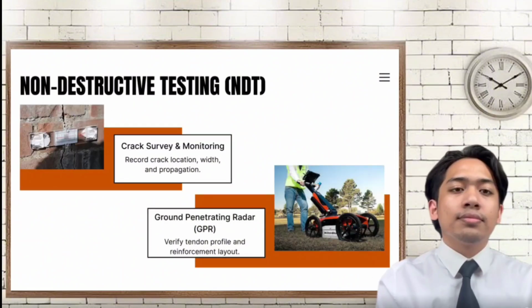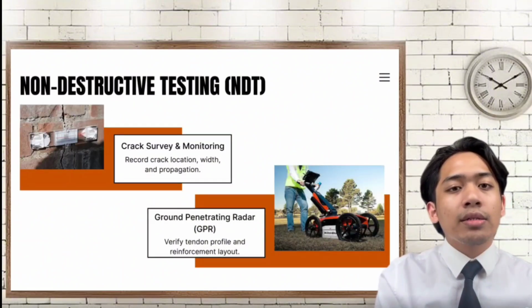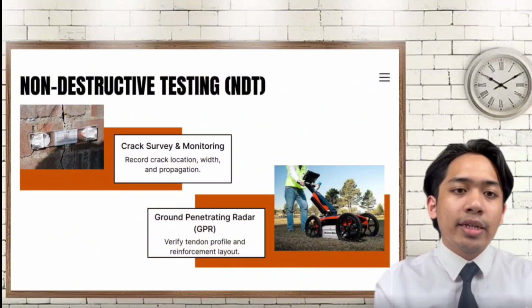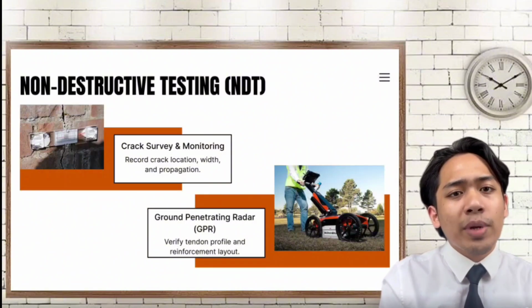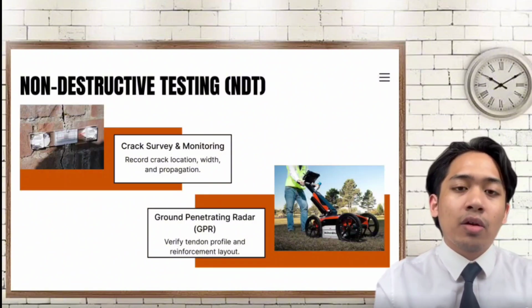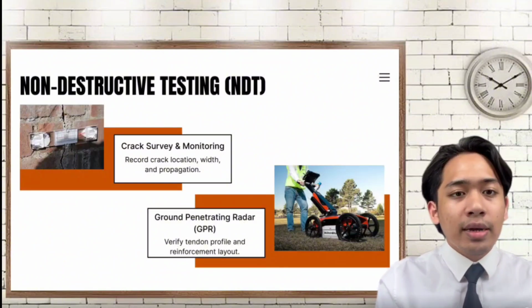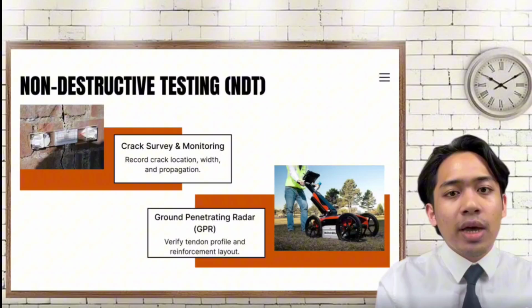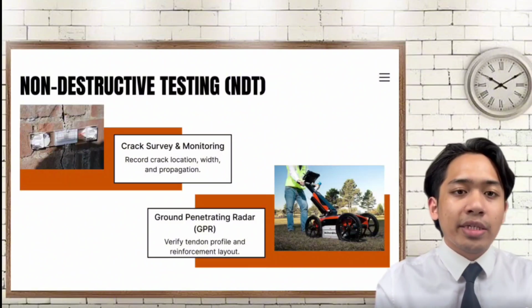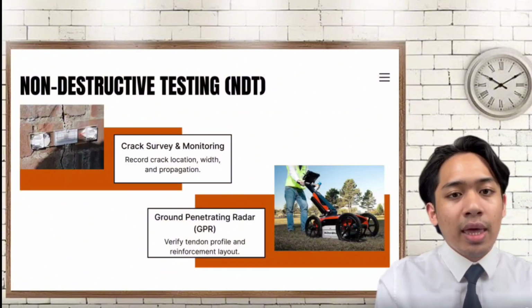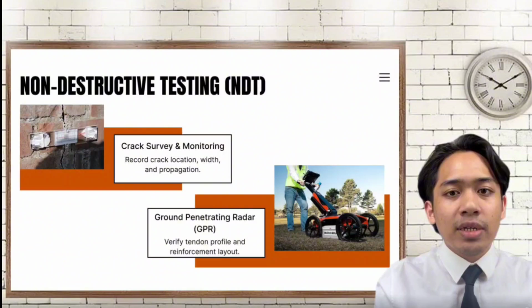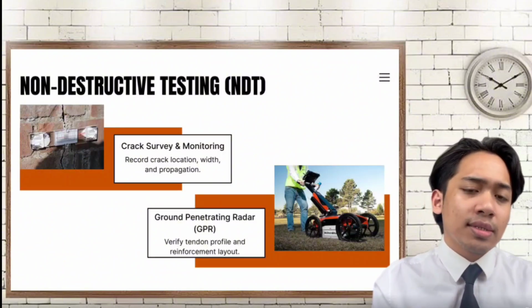Thank you. Other than rebound hammer and ultrasonic pulse velocity tests, additional non-destructive tests such as crack survey and monitoring, as well as ground penetrating radar (GPR), can also be carried out. First, crack survey and monitoring will be carried out to identify the location of cracks, measure their width, and observe whether the cracks continue to propagate over time. This helps in understanding the severity and pattern of structural distress.